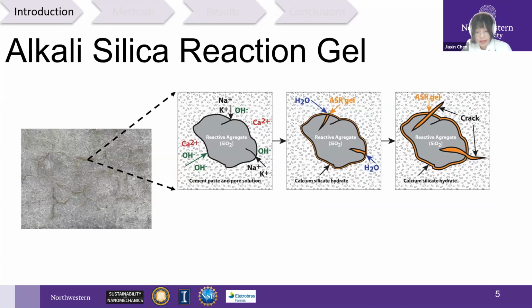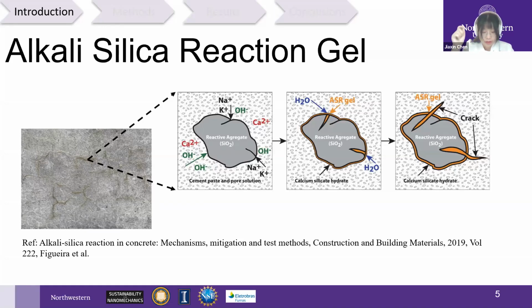Let's see where the alkali-silica reaction gel comes into place. Here's an illustration from Figueira et al., 2019. This reaction occurring between the amorphous or polycrystallized silica contained in some types of aggregates and the alkali from the cement paste produces a gel. That is alkali-silica reaction gel. In the presence of water, the alkali-silica reaction gel expands and produces a pressure on the solid skeleton, causing overall swelling and microcracks formation in the concrete.